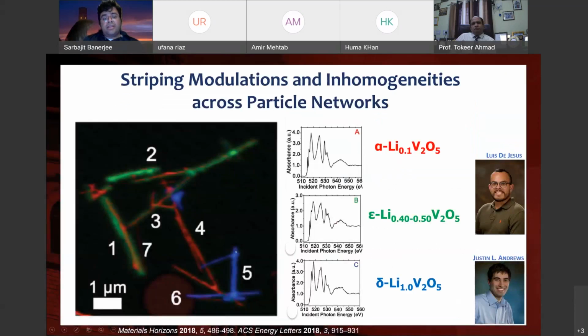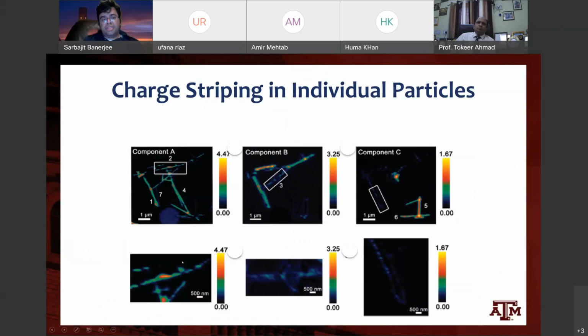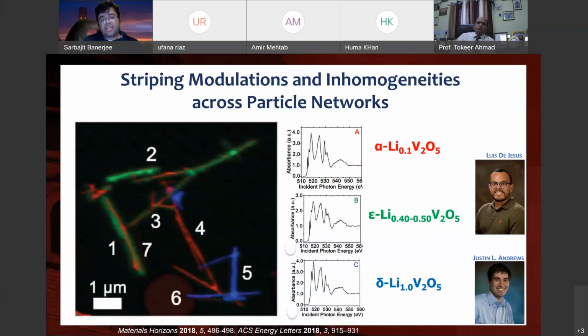And then when we look at networks of particles, we also see incredible amounts of heterogeneity, right? The red is relatively less lithiated, blue is more lithiated, green is intermediate lithiation. We see some very large degrees of inhomogeneities in lithiation across particles. And this is actually quite a substantial problem when folks make models for how batteries work. A lot of times they use very average, coarse-grained models that often do not take into account the very local nature of a complex cathode and of how intercalation reactions happen, often in a particle-by-particle manner.